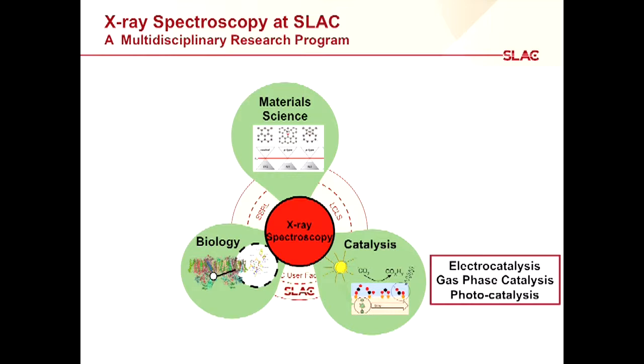For example, most catalytic reactions usually happen on surfaces. So assuming somebody has a very big particle, say tens or hundreds of nanometers, and something happens only on the surface, the very first layer, then if you come with a hard X-ray, practically you're going to probe the whole nanoparticle, and the actual process happens only on the surface. The complication this brings is that practically 99.9% of the signal you detect is going to be from material that doesn't participate at all.